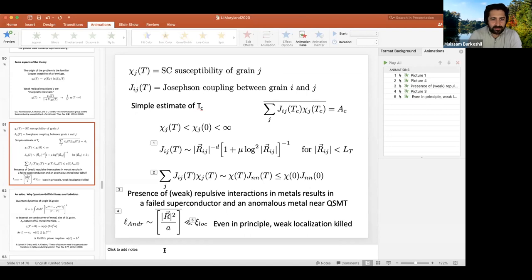Steve, I have a question. I'm not sure I completely understood something. Is this anomalous metal really different from just having some diffusive metal? So you mean, is there a phase transition between them? Probably not. But it's very, very different from a Drude metal. That is to say, the resistance is very strongly magnetic field dependent in a regime where a Drude metal would not be field dependent. It's got a value that's very low compared to the normal state value. So it's a metal in which superconducting quantum fluctuations have very long correlations and carry most of the current, and yet no matter how much you lower the temperature, they don't condense.